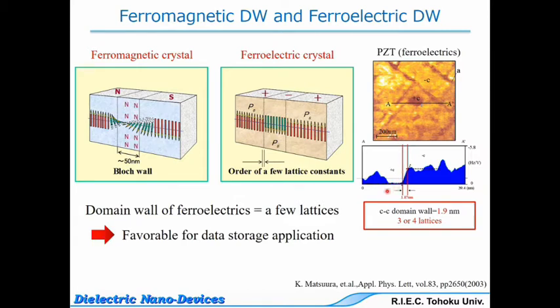So the actually measured domain wall thickness of PZT is 1.9 nanometers. It is 3 or 4 lattices. So the domain wall of the ferroelectric is a few lattices. And this is favorable for the data storage application.